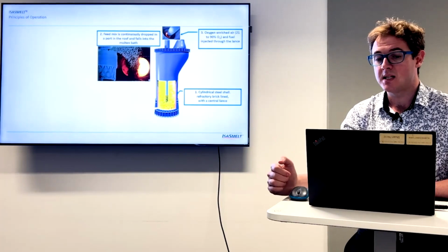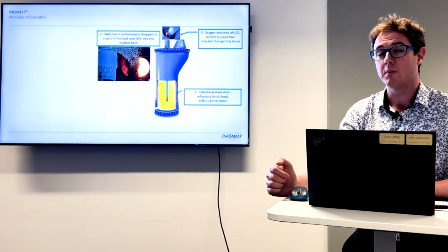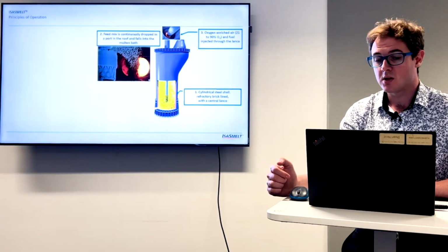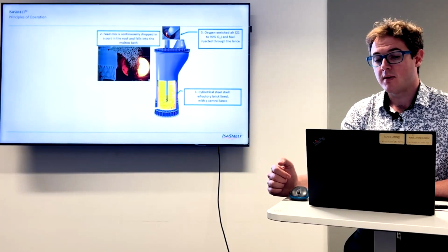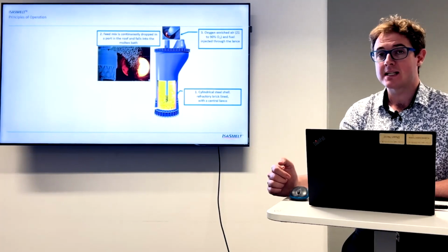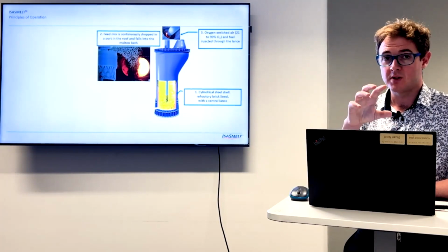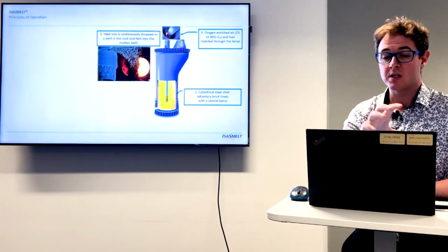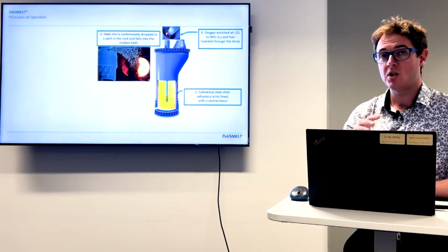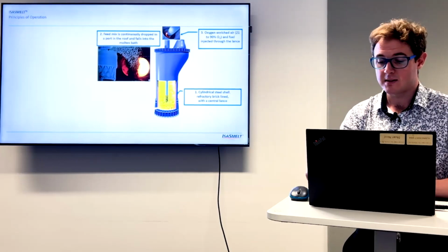We inject gases down the lance, from air all the way through to industrial oxygen, so 21 through to about 92+% oxygen through the lance. So this is where things happen. That oxygen goes into the slag and dissolves, and that then gets carried through to the feed materials. So that slag acts as the oxygen carrier in our smelting process. The gas goes down and reacts with the stuff that falls down the feed chute, or the feed materials in the bath, and then reactions occur. This then generates our molten products, so slag and matte or metals, as well as an off gas.